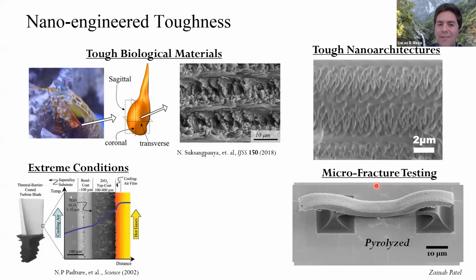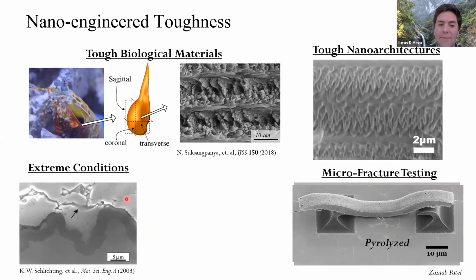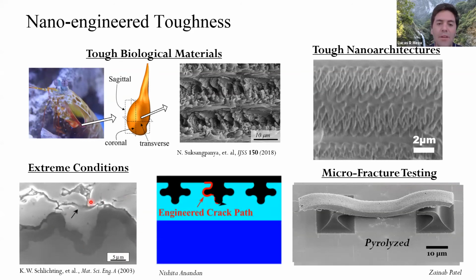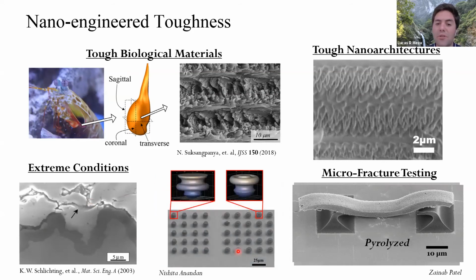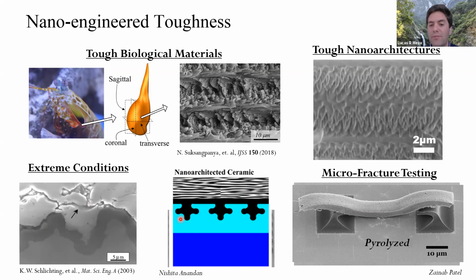In parallel to that, Nishita Anandan has been working on creating tough interfaces. This has applications in, again, thermal barrier coatings, where you have large thermal gradients that cause these layers to crack and delaminate. So you have these cracks forming at these high temperature change interfaces. Here we're actually able to create sutured interfaces or nano-sutured interfaces where we can design different sorts of architectures at an interface to then create a thermally shock resistant material.